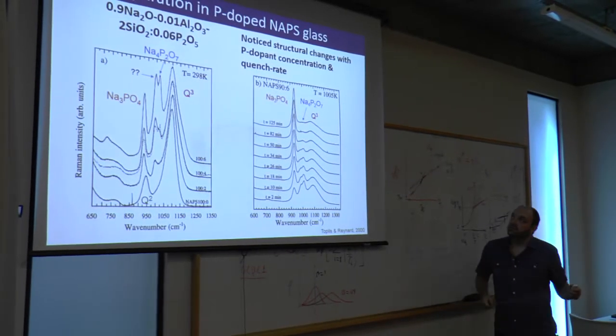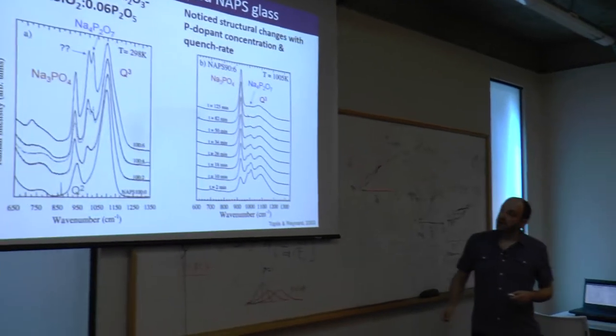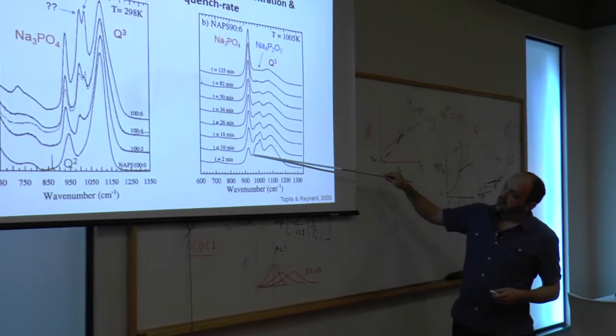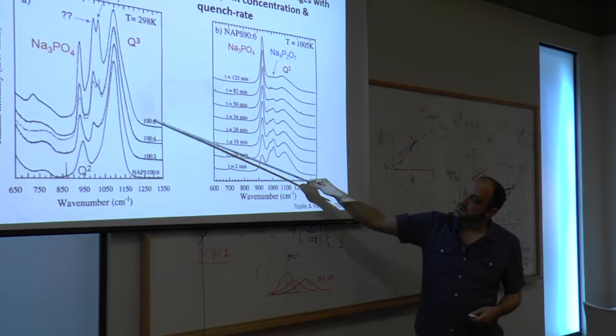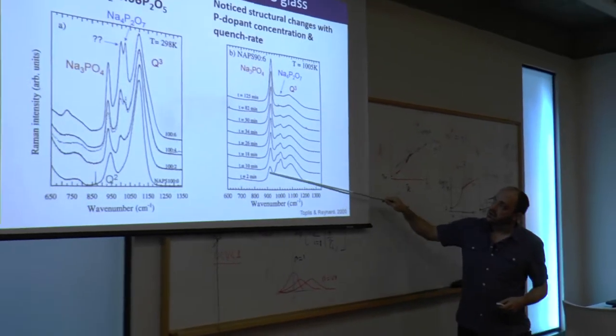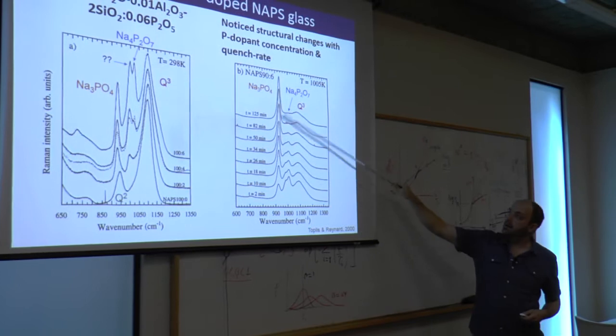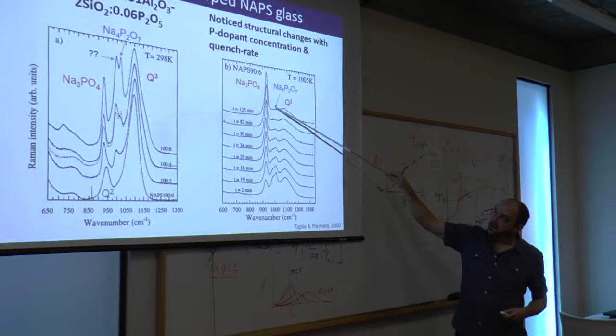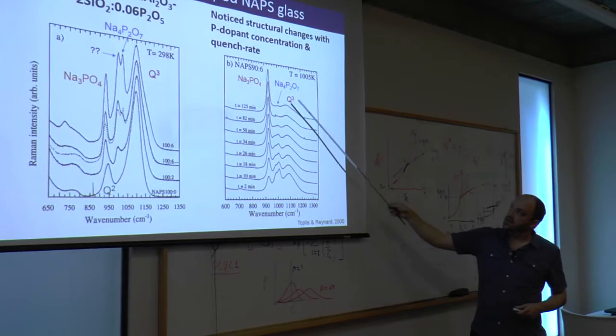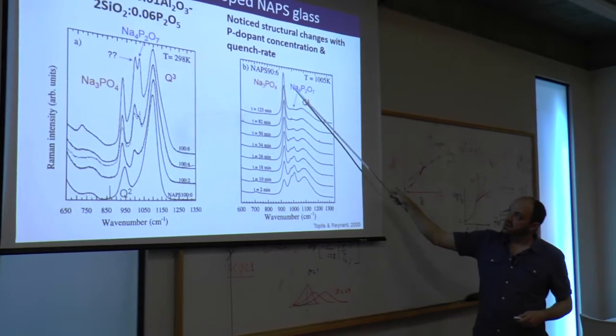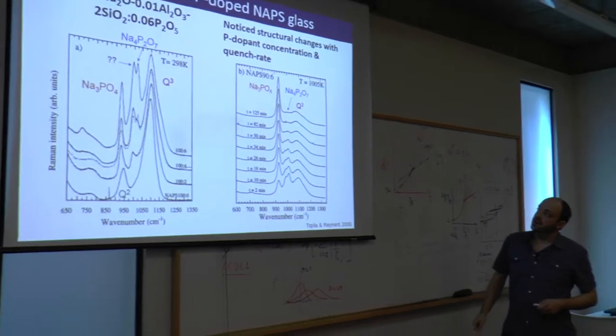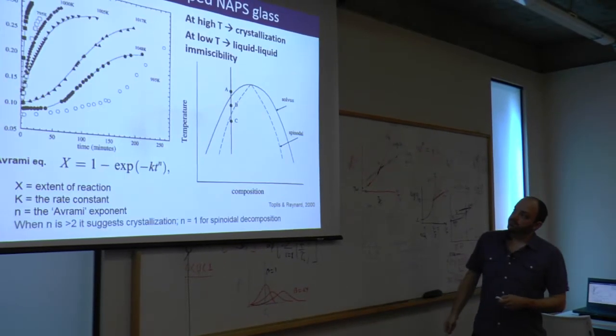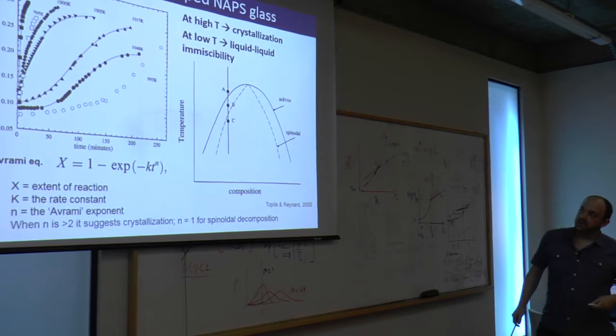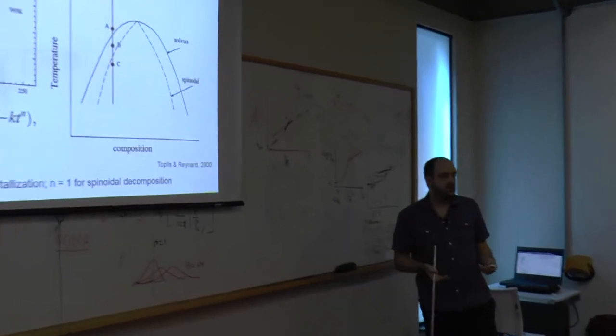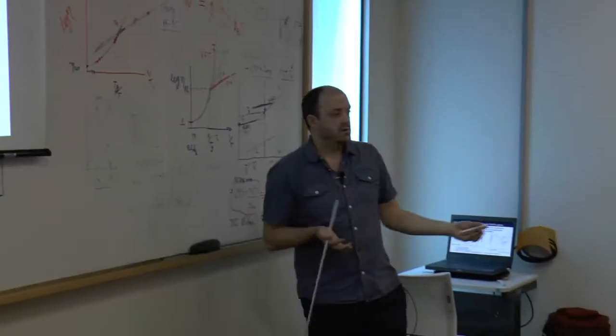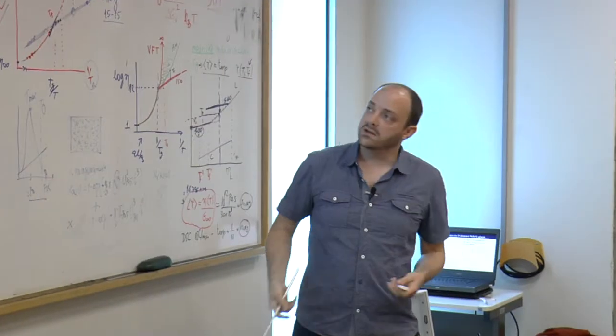Then they decided to follow this phase separation through time. And they saw that for this specific composition, the 6% of phosphate added, you saw huge growth in this low frequency band and the disappearance of these guys in the middle. And what they said is that we're actually dissolving this one and phase separating this one in the system through time. They went a step further and they tried to quantify how much phase separation was going on and what was happening at high temperature and low temperature, because they got different results depending on the quench rate.